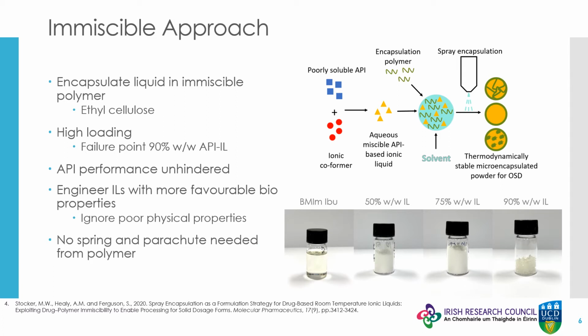Spray drying a solution containing the drug-based IL and an immiscible polymer such as ethyl cellulose allows for a remarkably high amount of IL to be contained in the powder. When produced in this way, we can solidify up to 75% weight-for-weight IL as a fine white powder and recover it as a solid at up to 90% weight-for-weight loading. At this extremely high loading, the product becomes more of a paste, and so this is taken to be the failure point of the system.